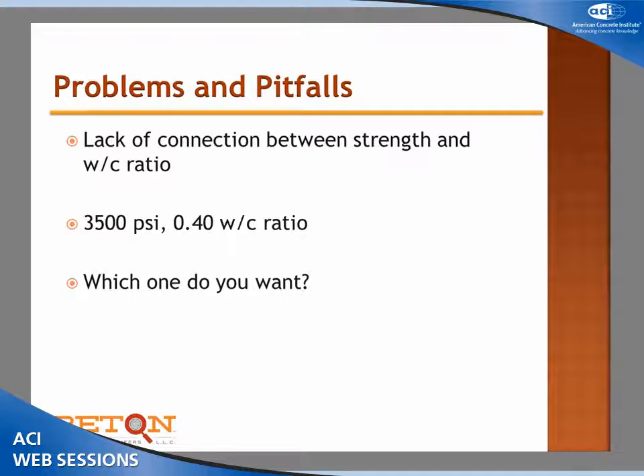So you write a specification and you hand it to me, the ready mix supplier, and it says the compressive strength required is 3,500 psi, and you want a 0.40 water to cement ratio. Now, which one do you want? And here's where you really fall into a trap, because if you measure strength and all the strengths are 4,500 or 4,000, you're going to be really happy, because I'm way over the specification. In fact, I probably never missed that specification, but you probably don't have a 0.40 water to cement ratio.